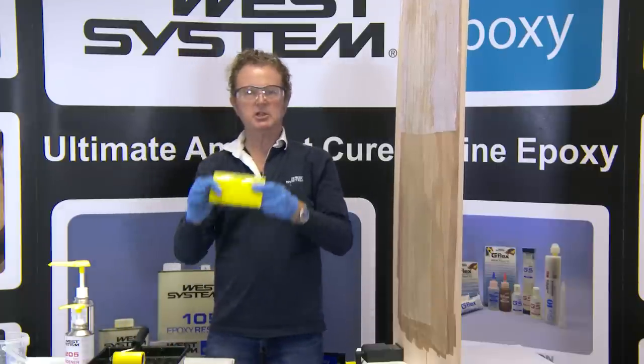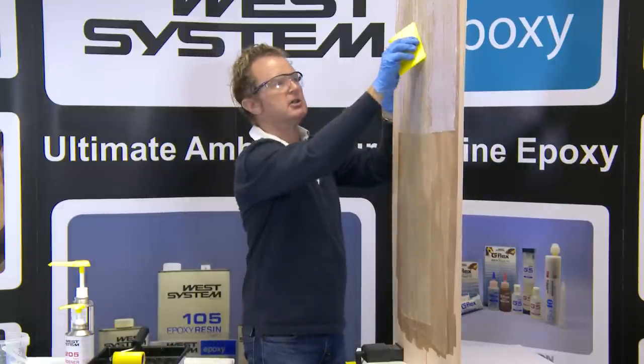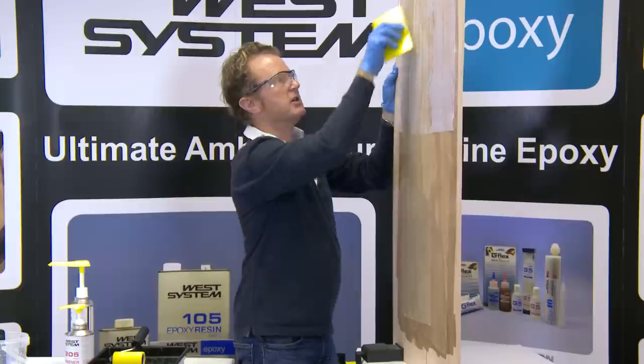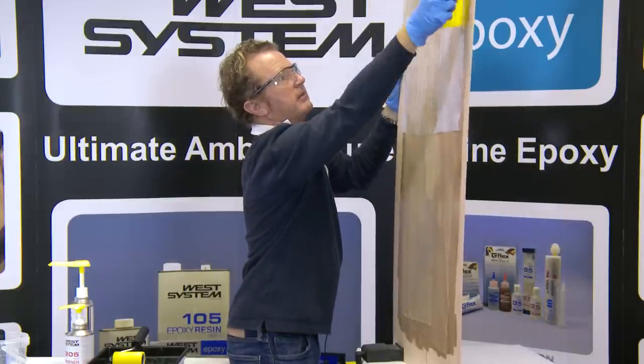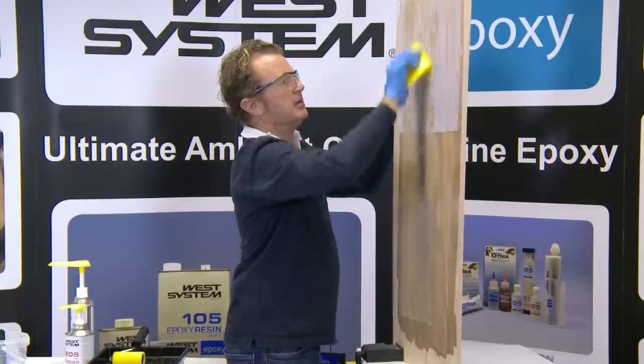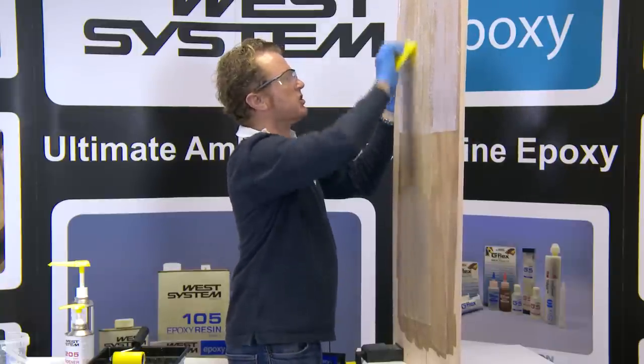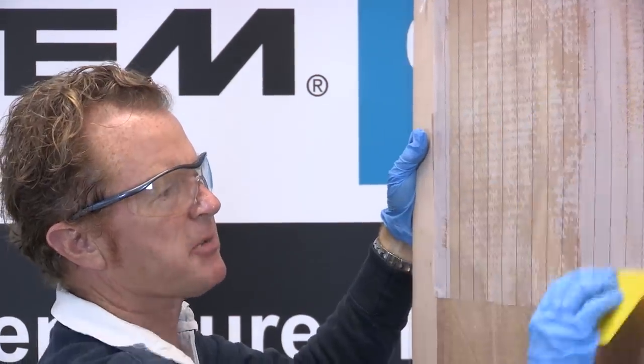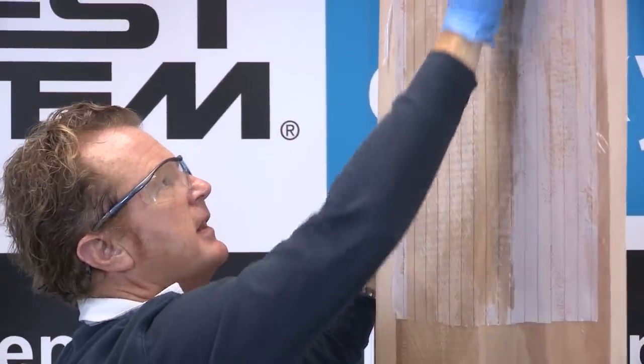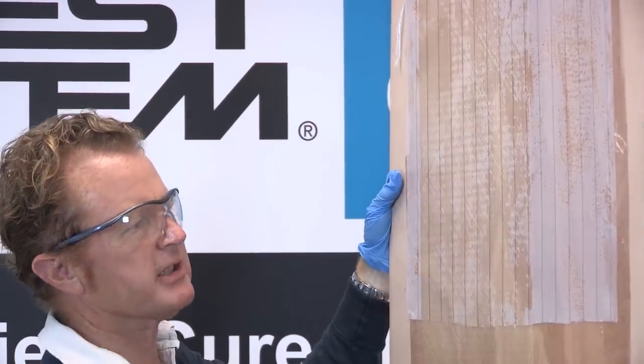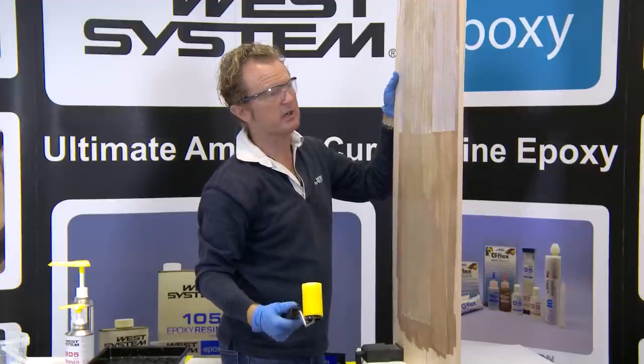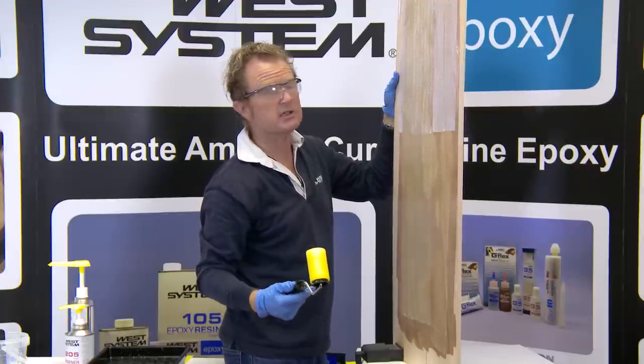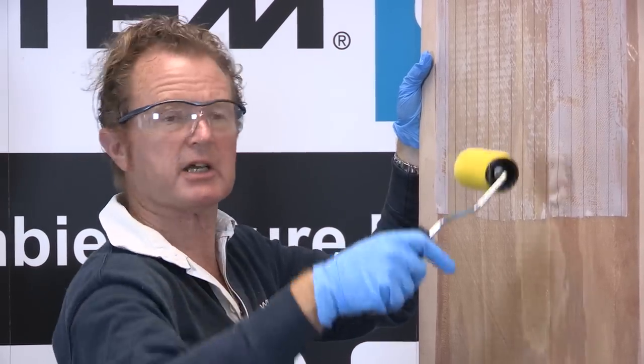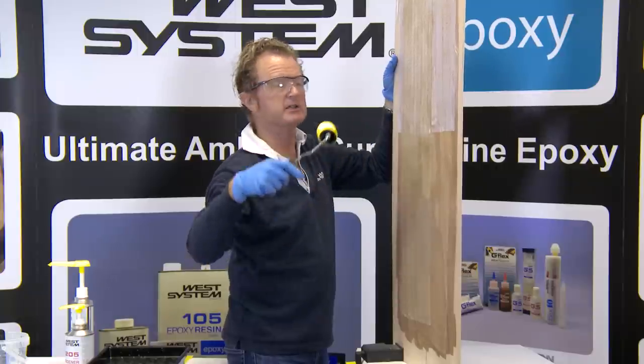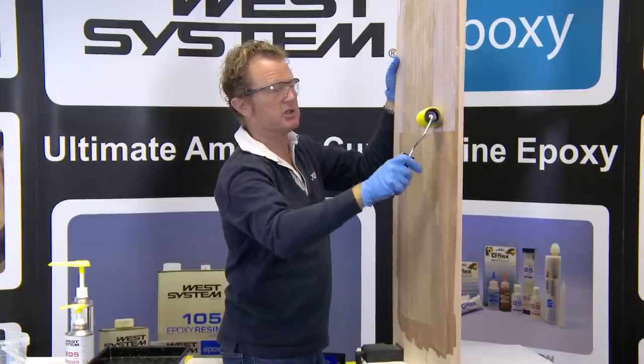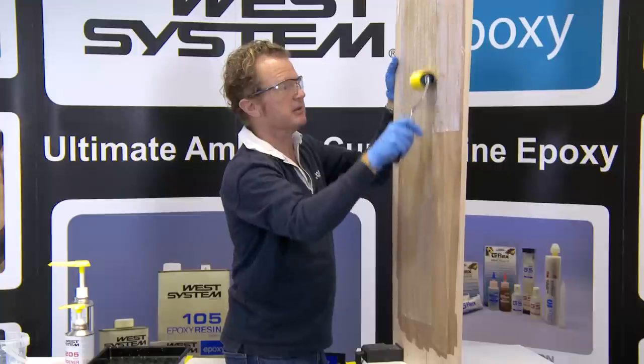And so it's at this moment that I can use a plastic squeegee to further consolidate my peel ply against the surface of my sheathed part. This will make your work look so professional, and it's so inexpensive, peel ply. It leaves a totally textured finish, which is fantastic for another process, be it either another coat of epoxy or a coat of paint or a secondary bonding, bringing in a bulkhead or bringing in further structure to a surface that's already coated with epoxy.